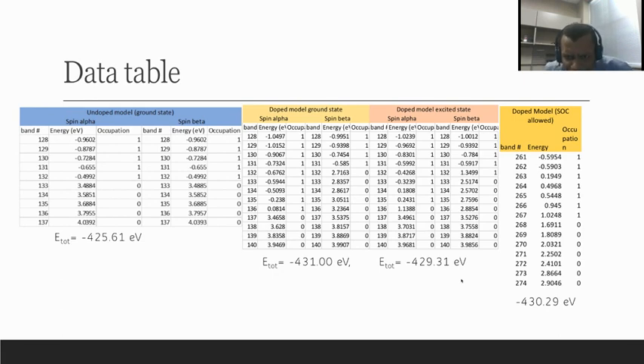Okay, so for the doped model at the excited state, we used N up down, which is the difference between the number of alpha and beta electrons. We chose this number to be 3, to allow for the spin orbit coupling to not be accounted for, but to force something that we could maybe understand or predict without actually doing the computations accounting for the spin orbit coupling.